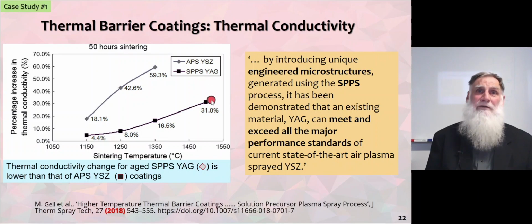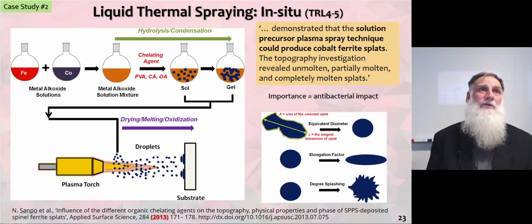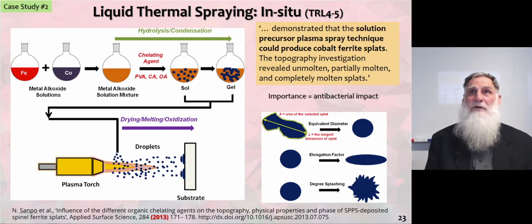So we have a thermal conductivity of 31% compared to something like 60% for the original APS coating, atmospheric plasma sprayed coating. And to quote the paper, by introducing unique engineered microstructures generated using the liquid thermal spray process, it has been demonstrated that an existing material can meet and exceed all of the major performance standards of the current state-of-the-art coating. So there is good news with regards to case study number 1. Case study number 2 really addresses a TRL level of about 4 to 5, where we